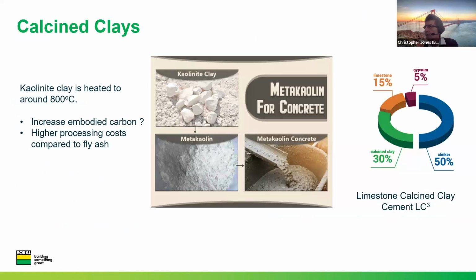Calcined clay is a type of clay called kaolinite, which has been heated to around 800 degrees centigrade. It calcines the clay, hence the name. It is also referred to as metakaolin. Companies in Australia are currently exploring suitable deposits of kaolinite, but so far it hasn't been produced in any significant quantities. The image on the right is a product called LC3, which is a blend of cement containing cement clinker, limestone, gypsum, and calcined clay. And they've been put together in ratios to optimize the performance of the cement.